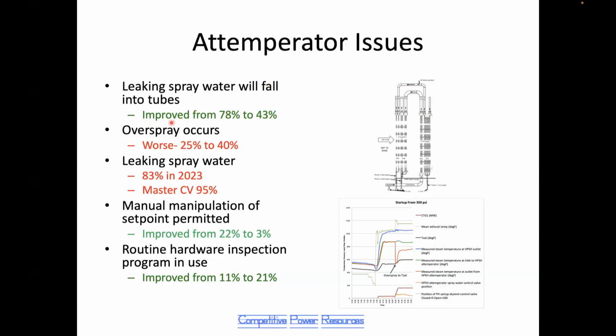Overspray in 2008 occurred in 25% of the units. Now it's gotten worse. Almost half the units overspray during startup or shutdown or low load. Leaking spray water wasn't measured in 2008. We weren't sensitive to that issue back then. But today, 83% of the units we survey have leaking spray water. This is the number one most common damaging problem.